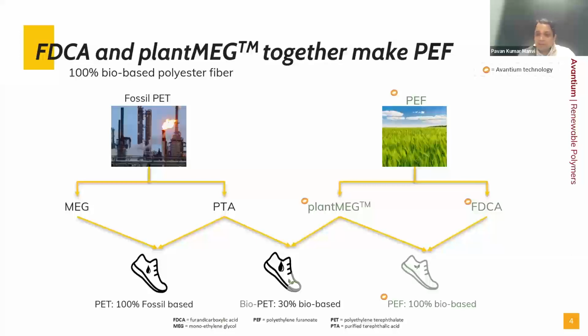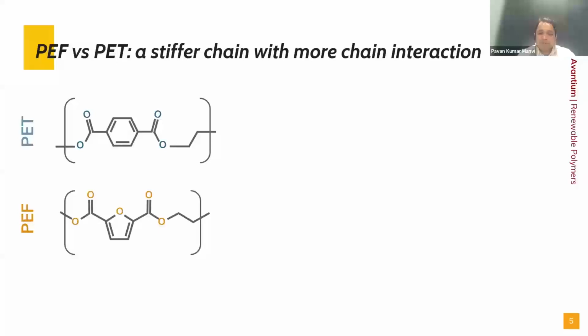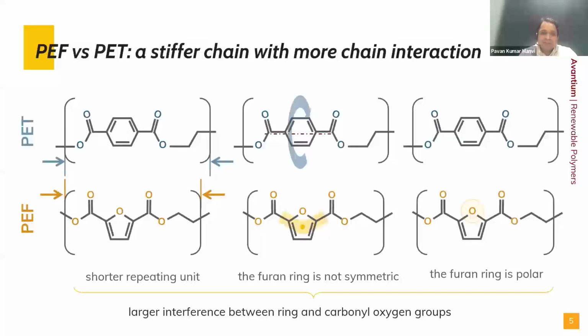So after looking at this overview, we can go into a little more detail about what the difference is at the polymer level between PEF and PET. Here we can see that the monoethylene glycol group makes the same chemistry as in the case of PET, but based on the difference between FDCA and terephthalic acid, there is a difference in the ring structure in the middle. Here you can see that instead of a 6 carbon ring, there is a 4 carbon ring along with 1 oxygen atom. So there is a 5 atom ring.